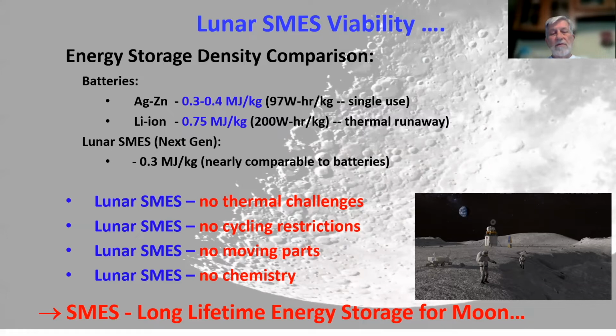The next generation lunar SMES, on the other hand, is about 0.3 megajoules per kilogram. So it's nearly comparable with batteries, but we have no thermal challenges with SMES. It likes cold temperatures. We have no cycling restrictions. You can cycle forever in terms of the supercurrent. There are no moving parts in this system, and there's no chemistry to worry about in terms of temperature and additives. So the SMES is a long lifetime energy storage possibility for the moon, which we would like to look at in the future. Thank you.